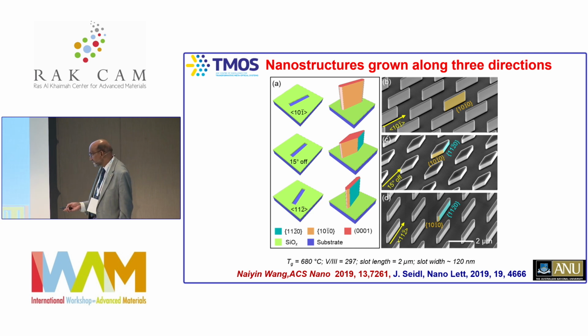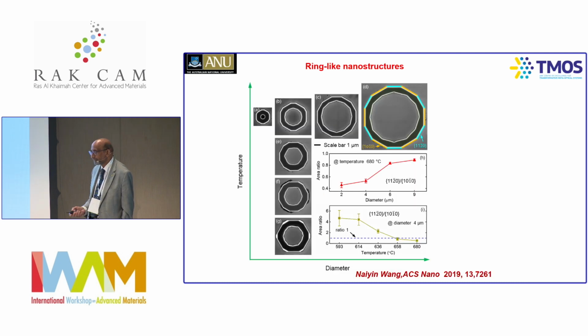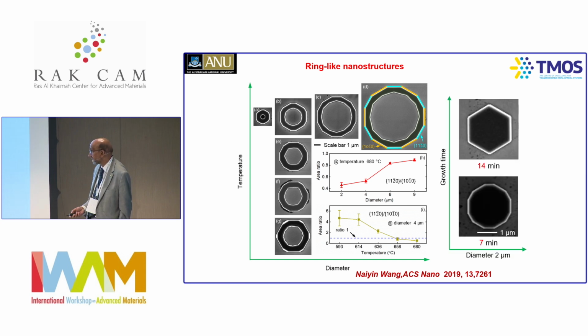And in fact, we've been using some of these membranes for demonstrating transistors with Adam Mikulich's group at University of New South Wales using indium arsenide nanomembranes and a similar process to what I'm showing you with indium phosphide. So what will happen if you open a ring? And again, you can see that you can get these beautiful ring-like structures with these alternating facets which I've shown you earlier. Again, I won't go into the details of various growth processes which Naiyin Wang has optimized.